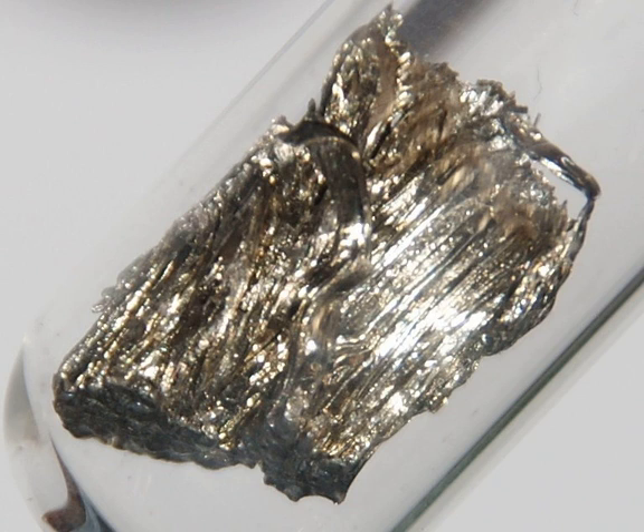relatively pure samarium has been isolated only recently, through ion exchange processes, solvent extraction techniques, and electrochemical deposition. The metal is often prepared by electrolysis of a molten mixture of samarium(III) chloride with sodium chloride or calcium chloride. Samarium can also be obtained by reducing its oxide with lanthanum. The product is then distilled to separate samarium (boiling point 1794 degrees Celsius) and lanthanum (boiling point 3464 degrees Celsius).